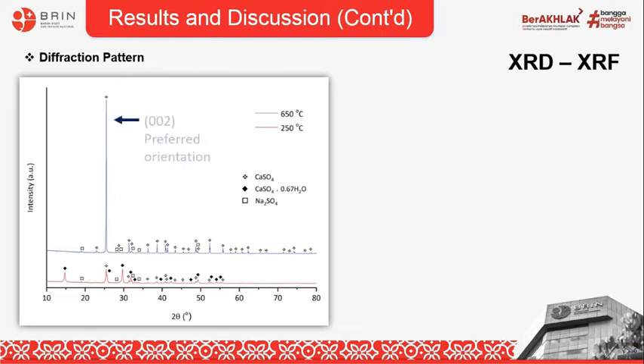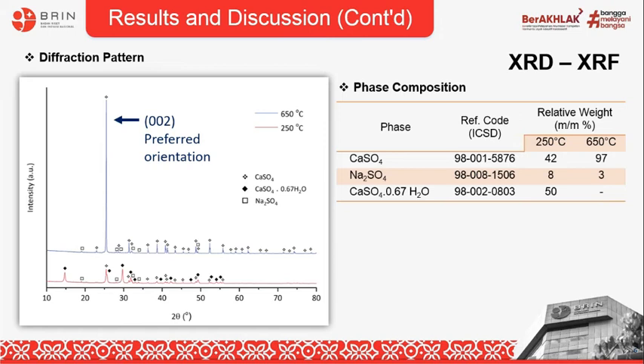The XRD pattern showed the preferred crystal growth orientation of the calcium sulfate crystal was the 002 plane, indicated by the peak at 2 theta of 25.5 degree, and the average crystallite size of the anhydrate phase was about 101.5 nanometers, estimated using the Scherrer equation by considering the broadening of the most significant peaks. The weight percentage of each phase was summarized in the table based on semi-quantitative analysis.